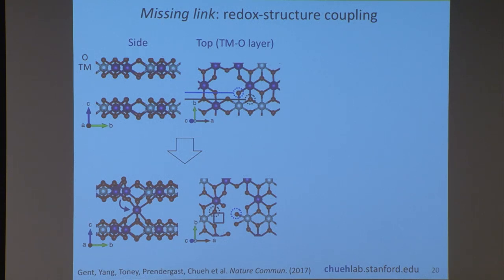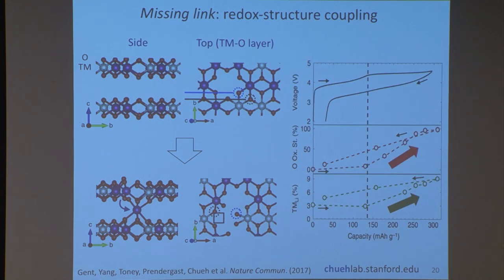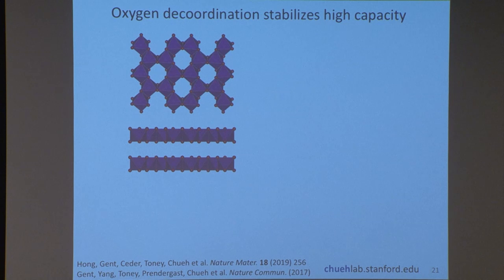And you can already see here, this leads to a very interesting local environment inside the metal layer. I'll introduce the defects more specifically in the next slide, but what I wanted to show you was, remember this extra capacity you're able to get, the more charge you can put into the material, 40% more. The increase right here in the capacity you get, almost all of it comes from the oxidation of oxygen. But this shouldn't work. And the missing link is as the oxygen gets oxidized, the transition metal also moves simultaneously. As you gain more capacity, these transition metal layers are coming down to the lithium layer simultaneously. This is very unusual, that they happen at the same time. And what we have done is to offer a very simple material chemistry explanation on why this happens.